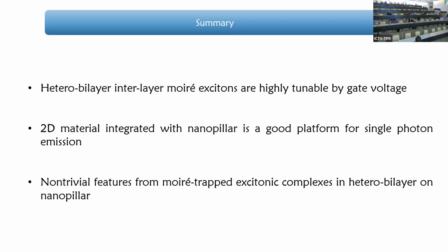Around 20%, 30% error bar, can you say? Well, the excitonic features are very stable, in the sense that if you see a peak, on the flat sample the best we got is about 8 meV or so, and in the pillar sample it came down to about 4 meV because the inhomogeneous broadening was significantly less.